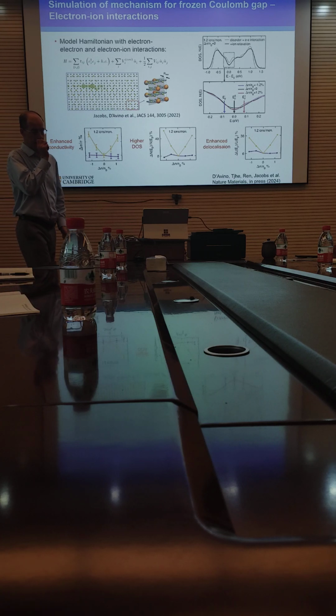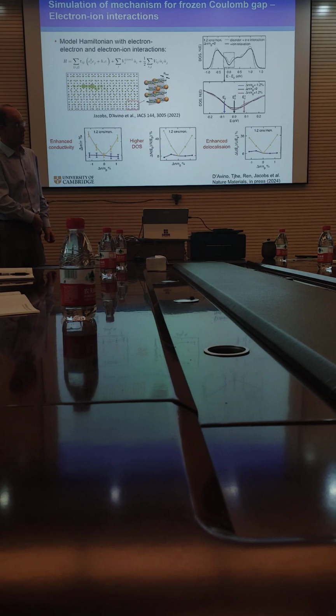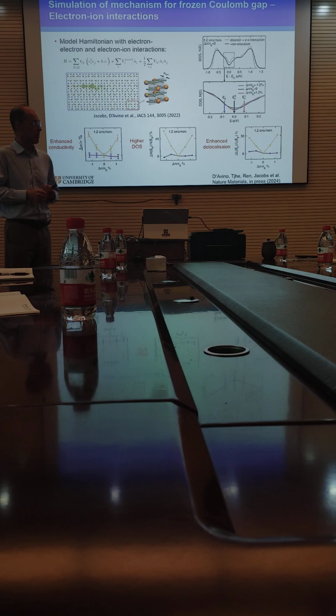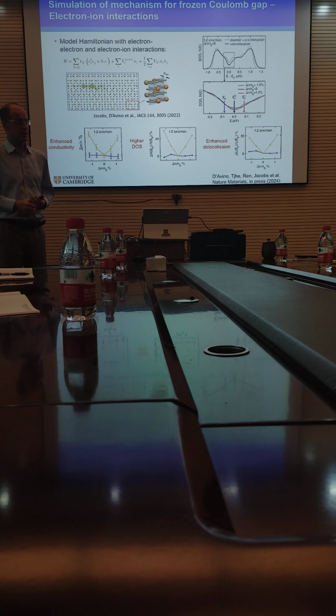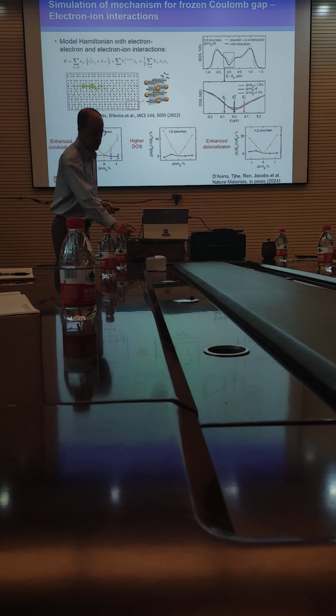So we have a fairly good understanding of what the physics is that's responsible for this unusual field effect response. And it's important for two reasons. The first reason is that it allows us to probe the Coulomb gap. We can understand the formation of this Coulomb gap in these materials. It's obviously quite an important feature of the density of states of these systems.